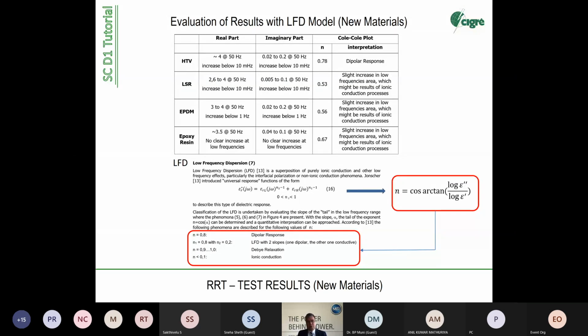An n of 0.9 to 1 is a classical Debye relaxation. Debye is theoretically at 1, and you have a strong ionic conduction if you are lower than 0.1. It's like, maybe you are aware of PD, partial discharge pattern analysis. I can remember it from my university time. It was a mess to read a PD pattern, and somebody said, okay, this is an internal void. No, this is a sharp edge. Or this is contact noise. Three people, three opinions. Today, industry responded to this, and in the measurement devices, they give you a kind of expert system to say, if you see this effect or this pattern, it may be a void rather than contact noise. So the help for the user is very important.